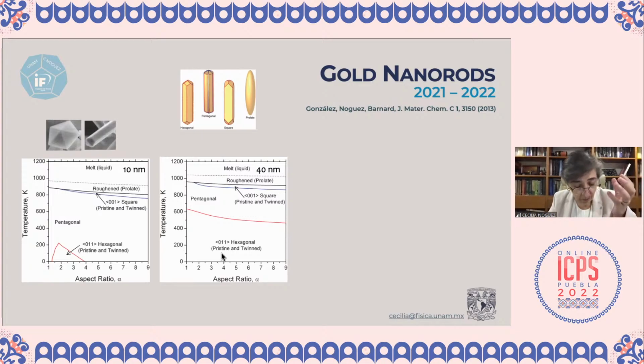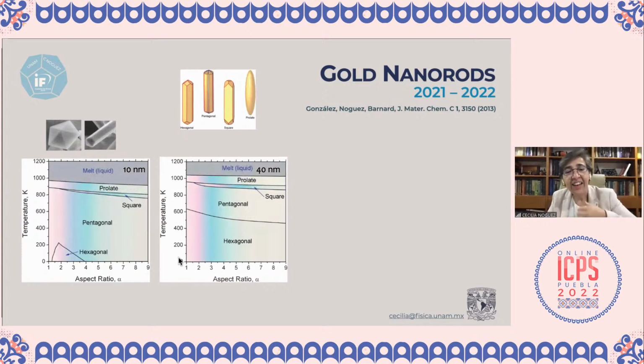Now, if we look at a sample with a given number of uniform nanoparticles, these hexagonal or pentagonal nanoparticles and so on, in a solution like water or toluene, what we see is that the color you will see at the end, in the transmitted light, will be the same independently of the shape or the volume of the particle. What it depends on is just the aspect ratio, that means the length as compared with the width of the nanoparticle.